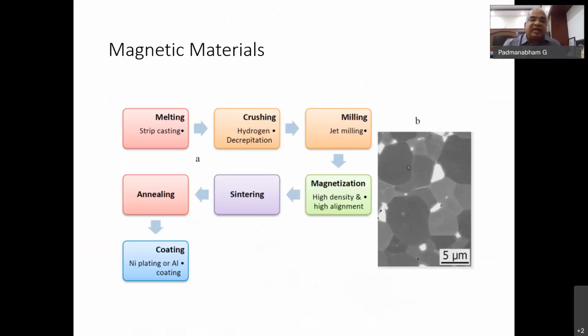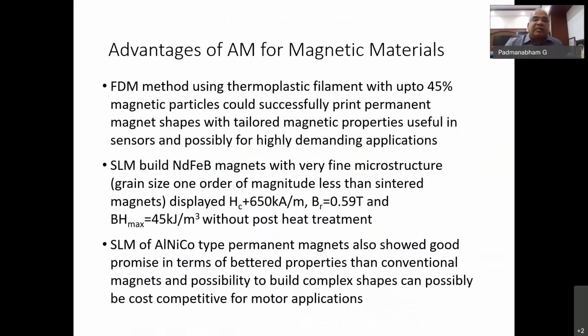Similarly, electric mobility requires magnetic materials with high BH product. Conventionally, the steps are melting, crushing, milling, magnetization for high alignment of your domains, sintering, annealing, and then oxidation protection by plating on top. These are the several steps through which you manufacture magnets. But when you use additive manufacturing for magnetic materials, today even the FDM method as well as the selective laser melting methods have been used to make permanent magnets. Almost 45% magnetic particles have been put into a thermoplastic filament, and the FDM method is used to make the shapes of the magnets that we are looking for. And then magnets are being made.